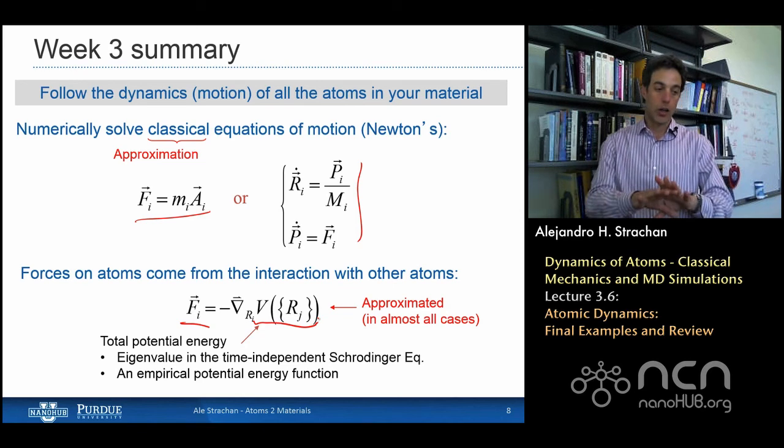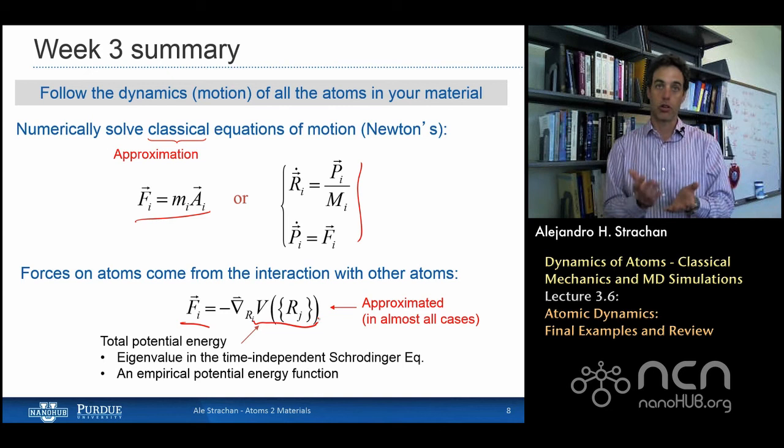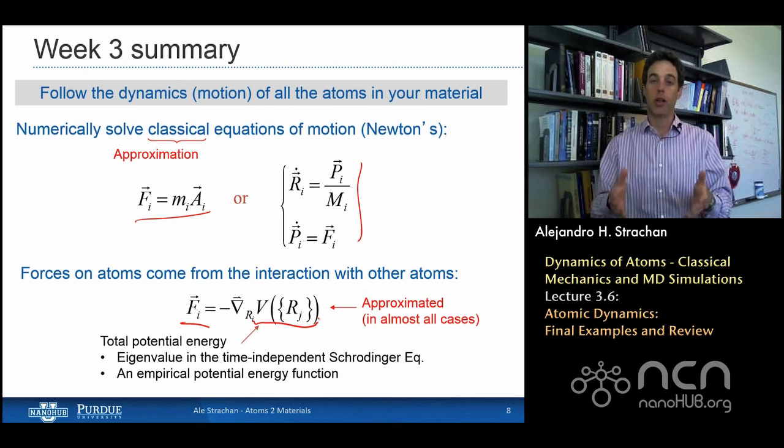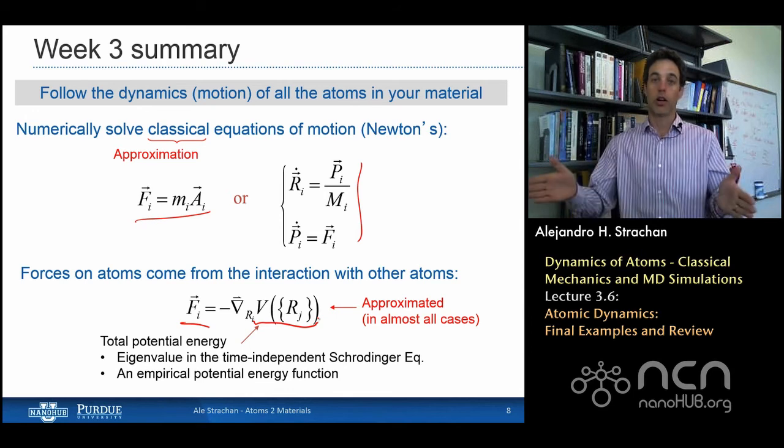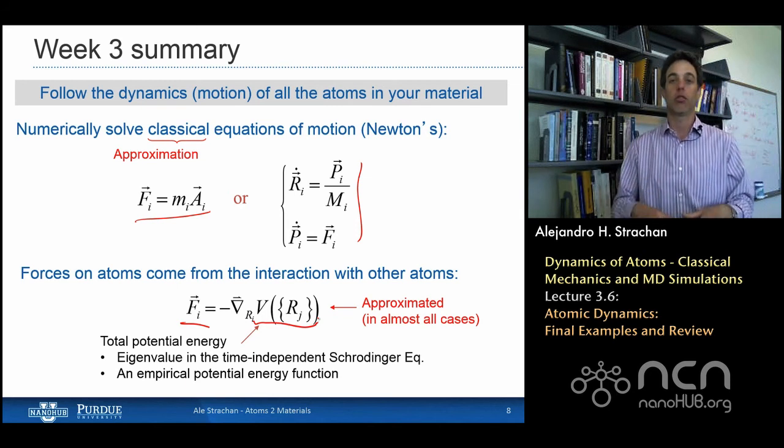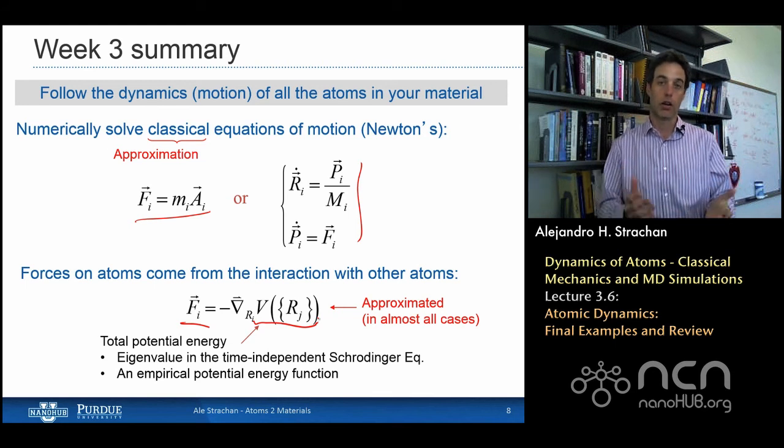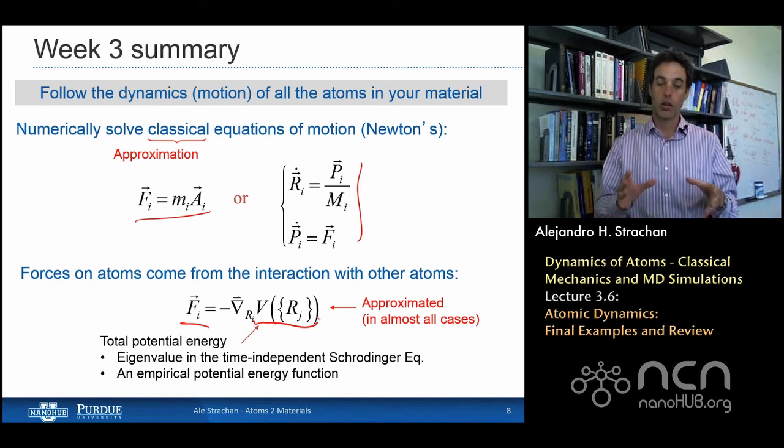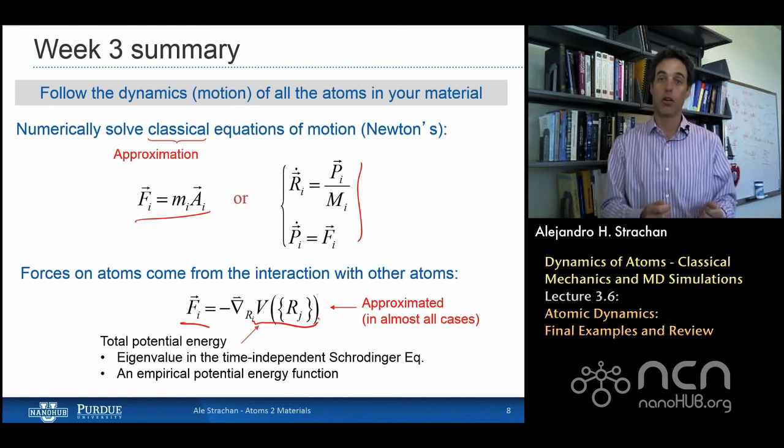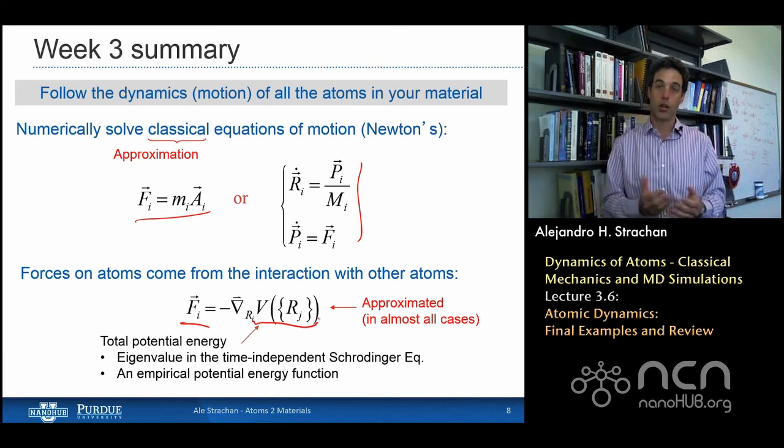However, if I restrict myself to relatively low temperatures where the potentials behave more or less harmonically, I can approximate, I can make a Taylor expansion of the potential energy and stop at the quadratic term, and then I can solve for normal modes or phonons if I'm thinking of crystals, and those descriptions are actually very interesting and very powerful to understand materials phenomenon.